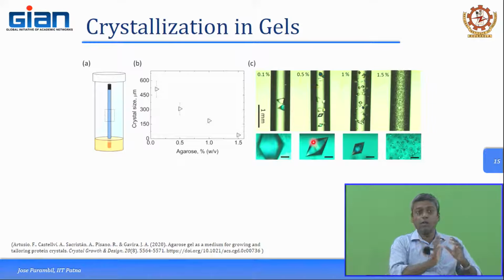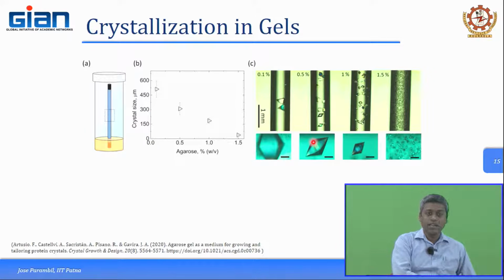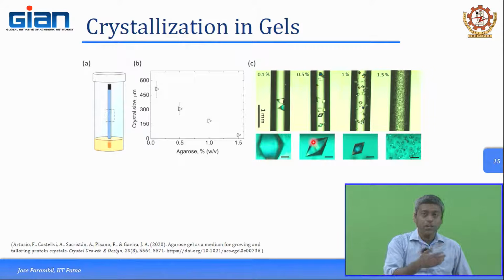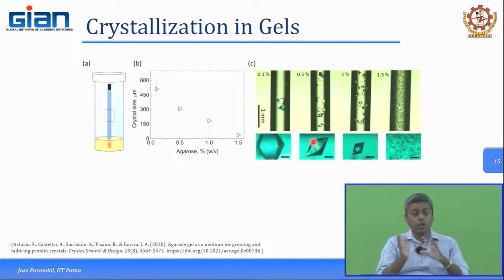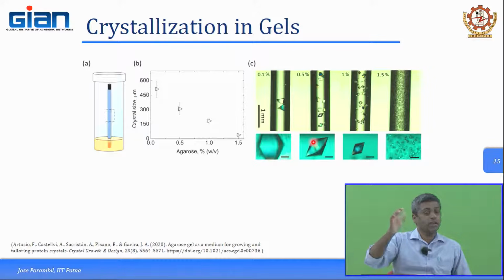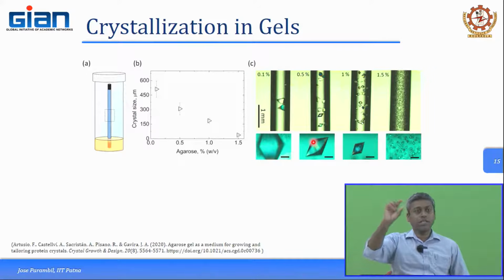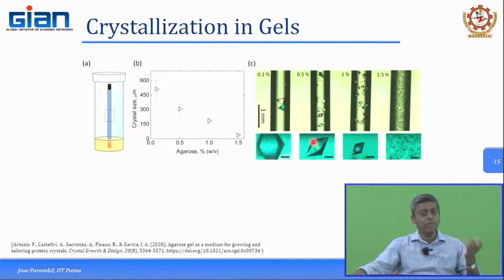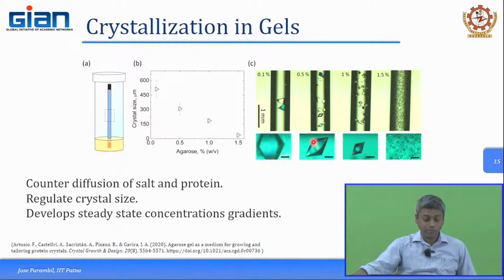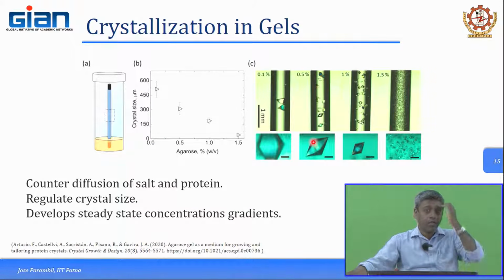So, that sort of preliminary analysis can also be done, because typically the diffusion rate of proteins as well as the salts can be figured out using experimental techniques, and that can be used to model the actual diffusion process and figure out at a particular time what is the concentration at a given position, and whether it has crystallized there or not. Then those sort of correlations can be useful for developing the process conditions which are required for separation. So, here both the counter diffusion of salts and proteins occur, and as I told you, you can regulate the size of the crystals.